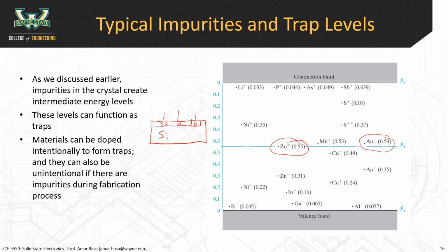So after those processes and after photolithography processes, there are often rinse steps where you're cleaning it off. It's cleaned with water. If your water happens to be impure, if you haven't cleaned the water well, you can get atoms, like gold atoms, let's say gold ions, just at the surface.